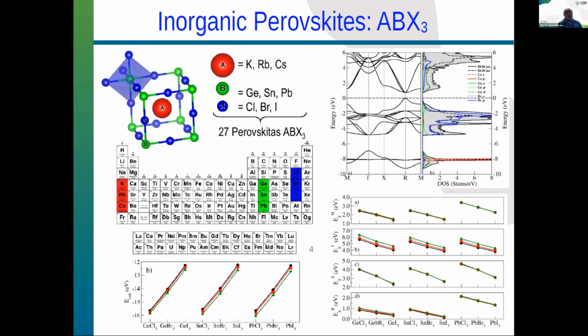And then shown here on the right side, at the bottom, we show the electronic band gap, in that particular case at the R point, because this is an ideal cubic structure. And then you can see that you can tune the band gap by changing the chemical composition, or rather, by changing the chemical species, that is going from chlorine to iodine. As you can see, there's a reduction of the gap, and all the systems follow the same trend whether you change the monovalent cation or not.